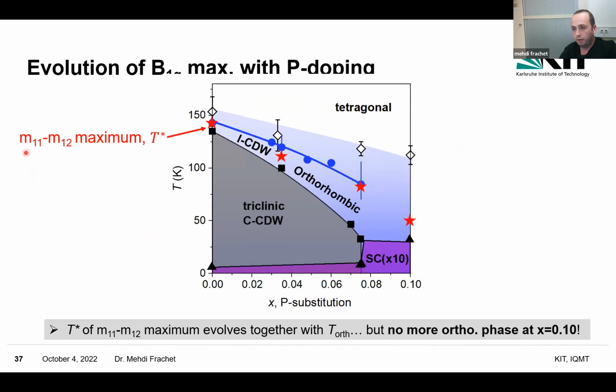So we can complete our phase diagram. So that's the T star temperature of the maximum elastoresistance, and you see how it goes in the phase diagram. And what you can notice is that it follows quite well the orthorhombic transition temperature as inferred by thermal expansion measurements. But at 10%, we still have a maximum, even though there is no more orthorhombic or triclinic structure that has been seen there. Okay, so that's very surprising, and I will come back in more detail about this in the last minutes.